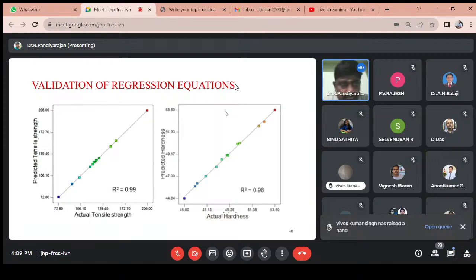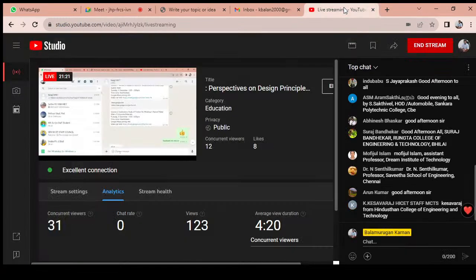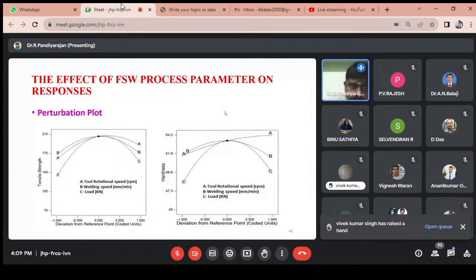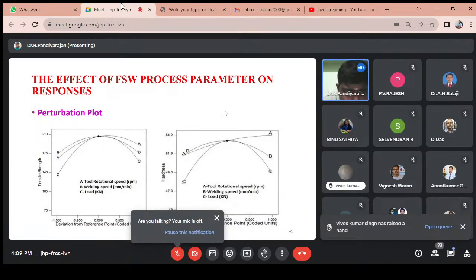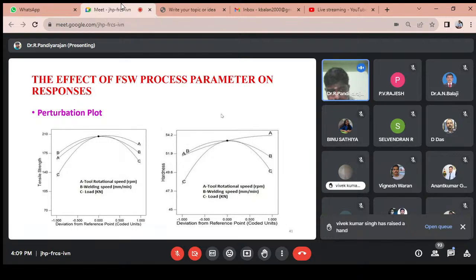After that we use the linear regression models, and when the error percentage is very small, we plot the perturbation plot. The perturbation plot clearly shows that we took 3 input process parameters: tool rotational speed, welding speed and axial load. Compared to the other 2 parameters, the tool rotational speed mostly affects hardness and tensile strength. So the most influential parameter is tool rotational speed.